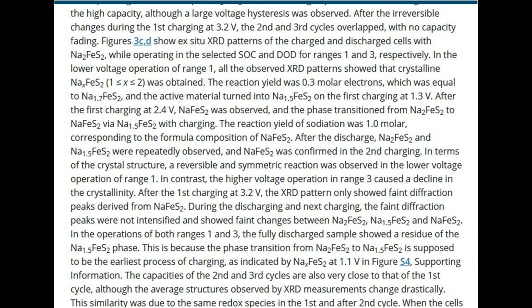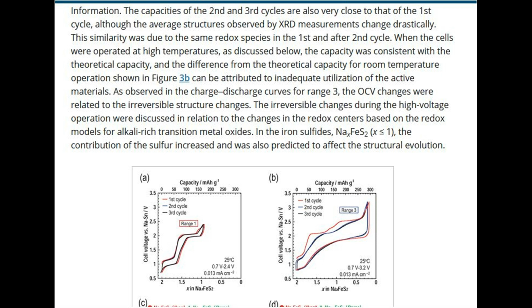The capacities of the second and third cycles are also very close to that of the first cycle, although the average structures observed by XRD measurements change drastically. This similarity was due to the same redox species in the first and after second cycle. When the cells were operated at high temperatures, as discussed below, the capacity was consistent with the theoretical capacity, and the difference from the theoretical capacity for room temperature operations shown in figure 3b can be attributed to inadequate utilization of the active materials.